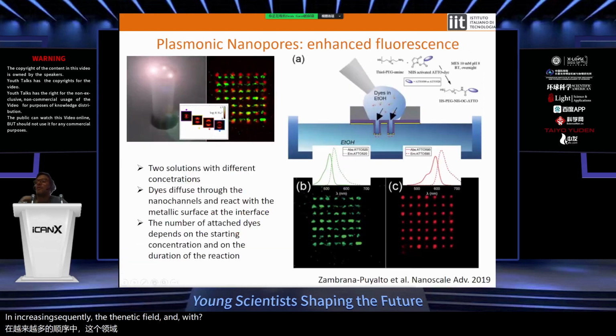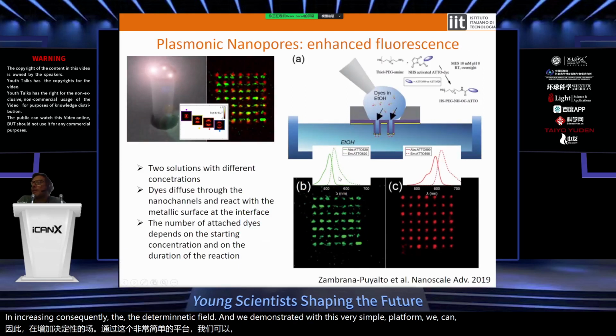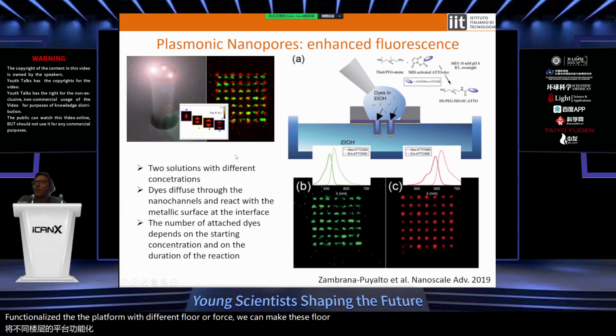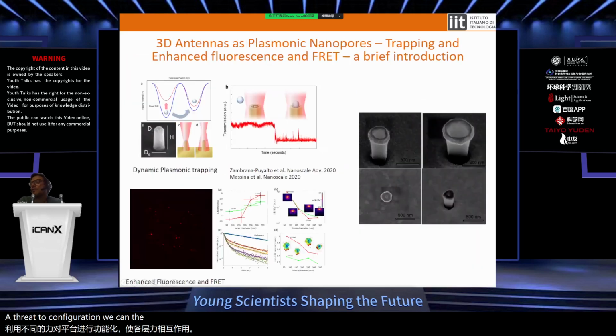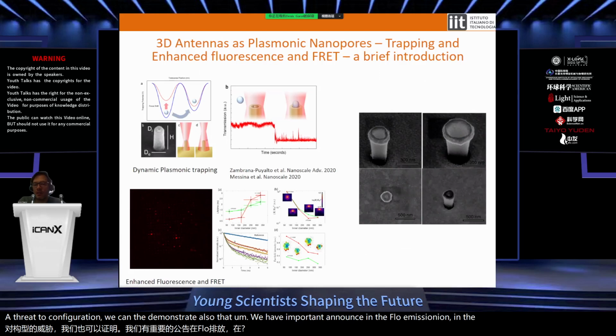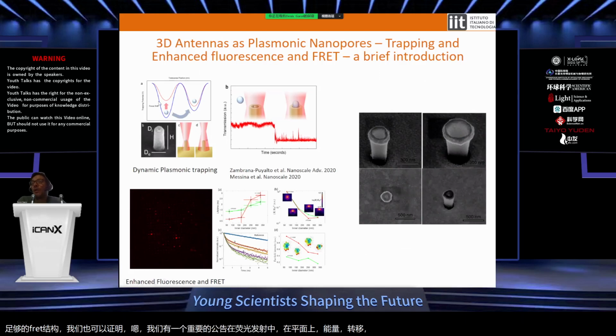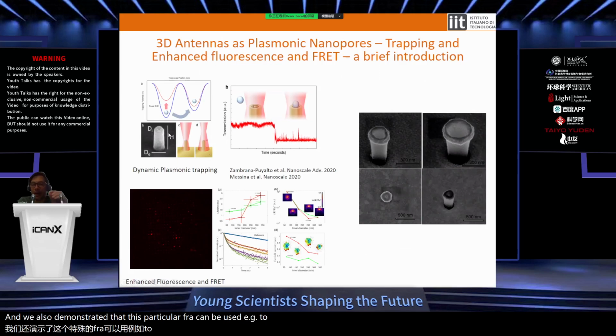We demonstrated that with this very simple platform we can functionalize the platform with different fluorophores and make these fluorophores interact in a FRET configuration. We can also demonstrate that we have an important enhancement in the fluorescence emission and in the FRET energy transfer. We also demonstrated that this particular platform can be used, for example, to trap and release a nanoparticle in a very easy way.